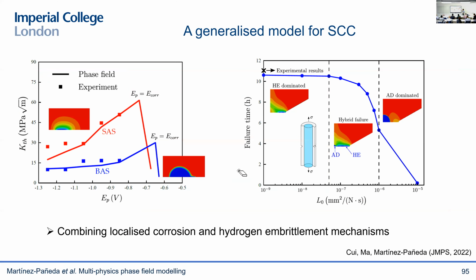So just to provide some examples, we have extended those corrosion models to combine them with those hydrogen models. So very often, as a result of the corrosive reactions, you have hydrogen atoms coming into the metal. So it's very difficult to know whether cracking was driven by stress corrosion cracking or by hydrogen. Our goal here was to develop a generalized stress corrosion cracking model where we didn't have to make any assumptions. We just say, this is my material, this is my environment, these are my loading conditions. And you can see that the model is able to capture the behavior across a very wide range of environments and also the interplay between corrosion and hydrogen.